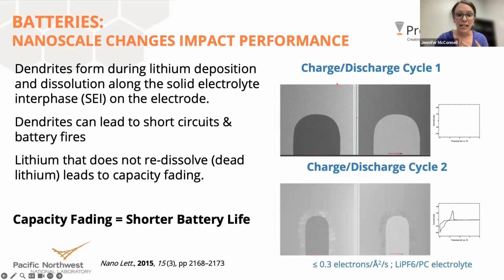And so what you're looking at here, in these videos, is a working electrode. This is a portion of a working electrode that's inside that Poseidon system, inside the TEM, and it's surrounded by a liquid electrolyte. Here's your electrolyte here. And in this first video, we're running a charge-discharge cycle, and you can see the voltage, the potential there. And as we sweep in the negative direction, you're going to see lithium dendrite formation on that working electrode.